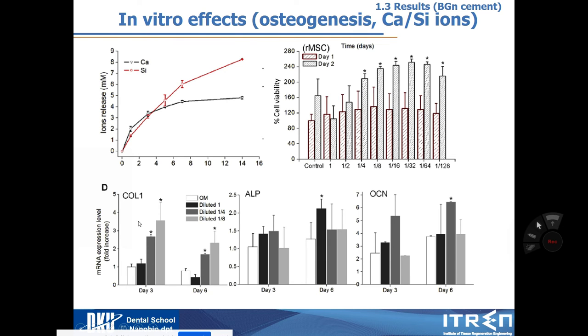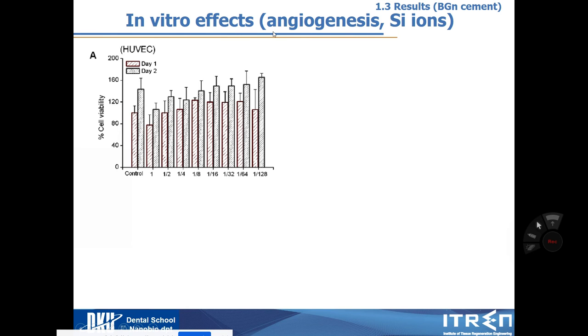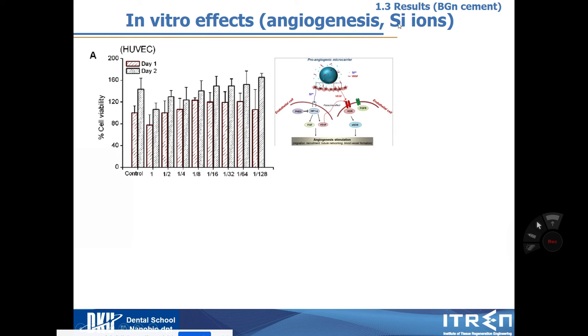And then when I check their bone differentiation, this time I use the rat MSC and check the bone formation. And I check that collagen 1, ALP, OCN increased in this diluted cement extract compared to the media-only control group. And then I can expect some increased angiogenesis from the silicate ion. Similarly, at the same time, when silicate ion is released from a certain biomaterial, it can activate angiogenesis, some blood vessel formation.